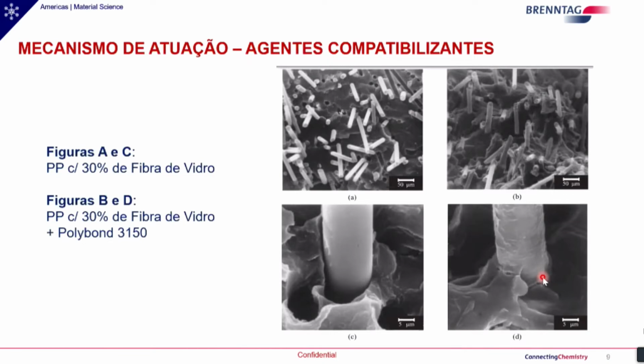As this is wet, you increase the interaction between the polypropylene matrix and the disperse phase, which is the glass fiber. So we increase this connection, so the mechanical strength is then transferred from the polypropylene matrix to the glass fiber. And of course, the glass fiber has more mechanical strength. As a consequence, we empower the mechanical properties of the composite.